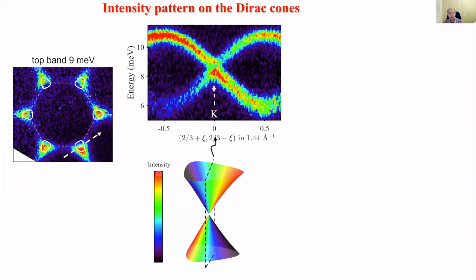So one unusual feature here is that if we were to represent the conical dispersion surfaces touching at the K point and paint them with intensity as predicted by the theoretical model, this intensity is not uniform around the core, but it's strong on one side and very weak on the other side, and exactly in antiphase for the bottom band. So the slice that I've shown here is in this transverse direction, where both modes are clearly visible.